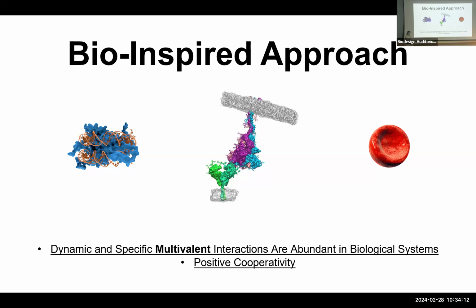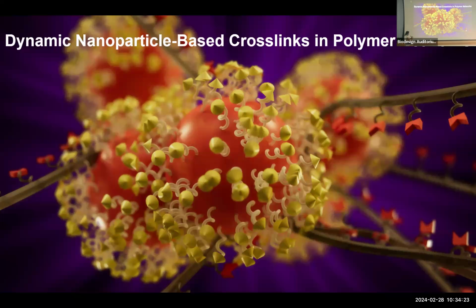And you can introduce that concept in these polymers. One way to do that is by introducing nanoparticles, where you're assembling polymers and nanoparticles together. Because a nanoparticle has a larger surface area, you can have that multivalency in polymer networks. So that's the approach that we have taken to make these self-healing materials have a lot higher binding interactions, so that we can solve this trade-off that we are seeing with the self-healing materials that have been synthesized thus far.